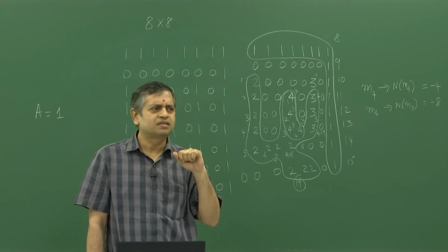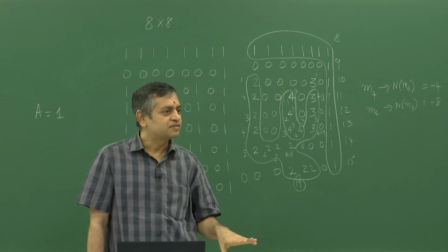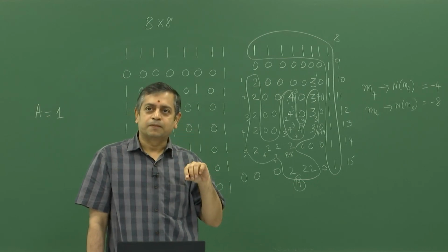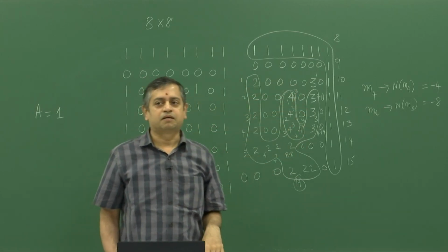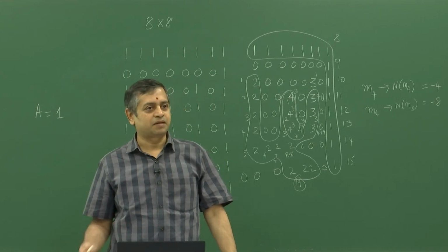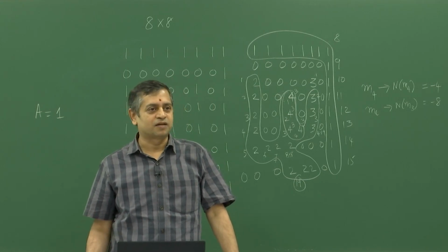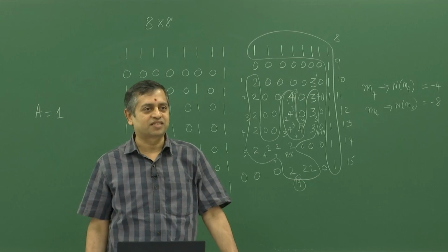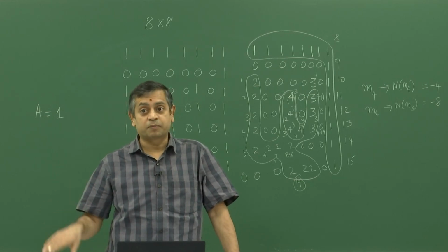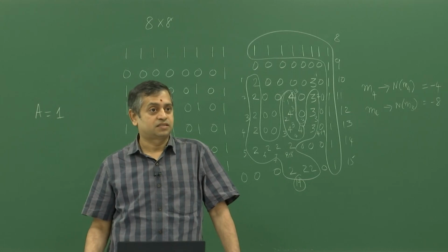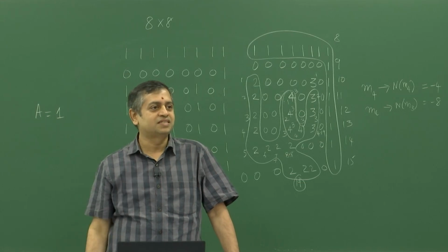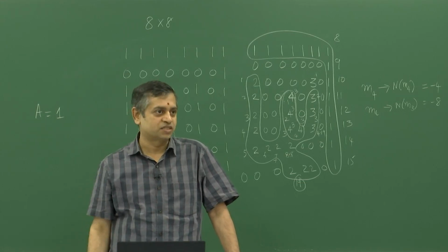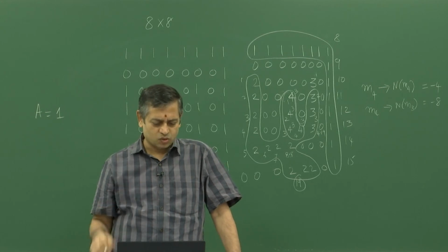We also did something. We generally tend to think that the larger volume fraction phase should be the matrix phase, but in some cases it can be inverted. A classic example is nickel based superalloy. You will have a very thin channel of gamma and a large volume fraction of gamma prime, more than 50%, but still gamma prime will remain as a precipitate, that is, as islands. You can't start on one gamma prime and hope to reach the other end, whereas through the gamma channels you can. So that happens, and this is known as phase inversion.